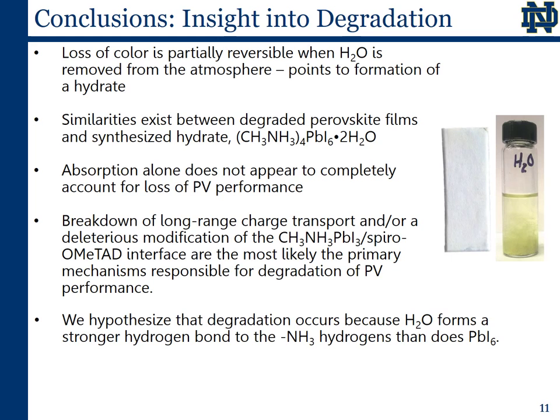Additionally, it does not appear that the loss in absorbance completely accounts for the loss in photovoltaic performance, an observation which points to another mechanism being responsible. We postulate a breakdown in the long-range charge transport or a modification of the perovskite spiro-OMeTAD interface as perhaps the most likely reasons for the degradation of photovoltaic performance. However, other possibilities exist as well.